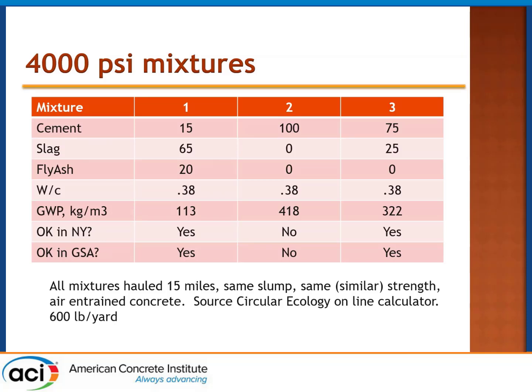So I found a source, Circular Ecology, that has an online calculator. It is supposed to calculate what the global warming potential, CO2 equivalent, is of your concrete mixture if you put a bunch of data in. I had it hauled 15 miles. It's the same slump, similar strengths, designed to be 4,000 psi air-entrained concrete, and 600 pounds of material per yard. And this is what I came up with.